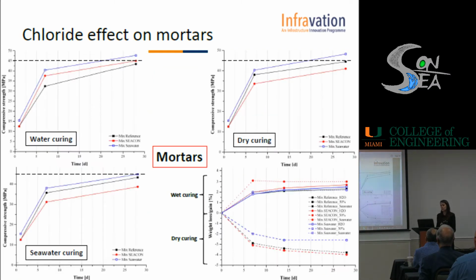So we also performed tests on mortars. Our three mixes were: mix reference, with reference cement and fresh water; mix SEACON, with SEACON cement and fresh water; and the third, mix seawater, with reference cement and seawater. In all the cases, we produced mortars according to the European standard UNI EN 196 part 1. So we used 450 grams of cement, 1,350 grams of normalized sand, and 225 grams of water. We also used the mixing procedure of the standard.